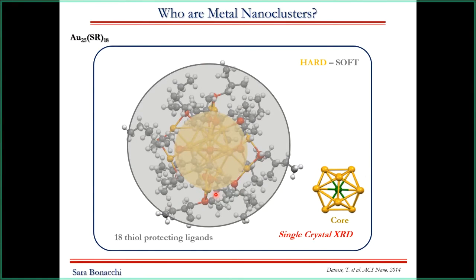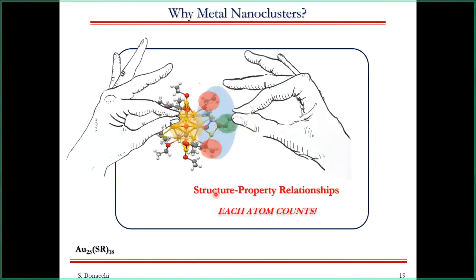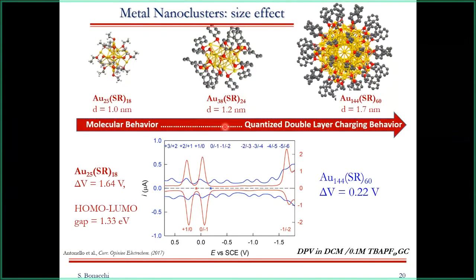So this double hard-soft nature of the cluster is very fascinating, and in particular the most fascinating aspect in this field is the possibility to really tune atom after atom the electrochemical and optical properties of this cluster. So basically we can really change one single ligand or one single metal atom in the core, and in this way we can dramatically change the physicochemical properties of this cluster, with a strong structure-property relationship. So we are sort of magicians that can play with this structure to tune their optical and electrochemical properties as well.